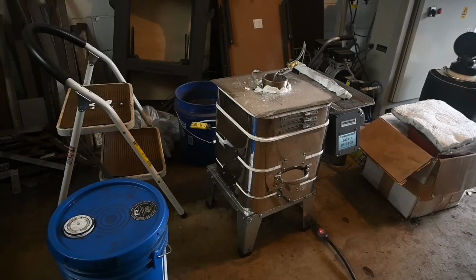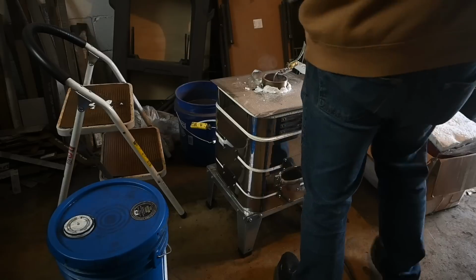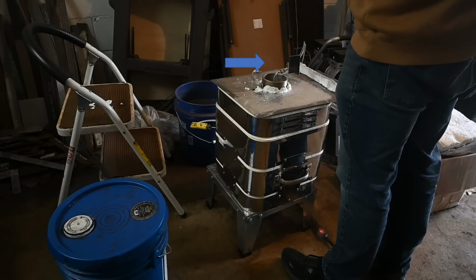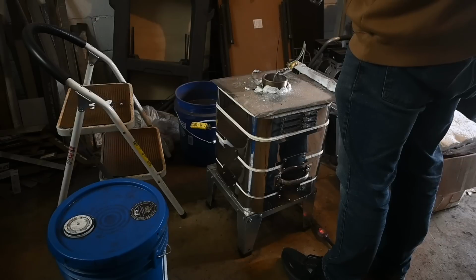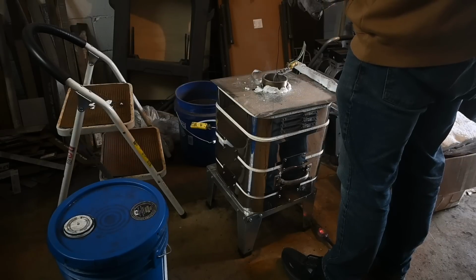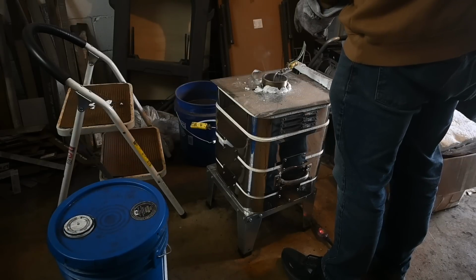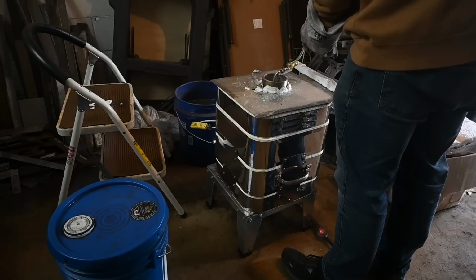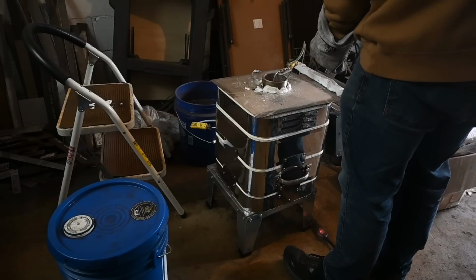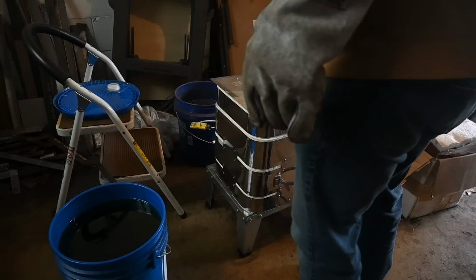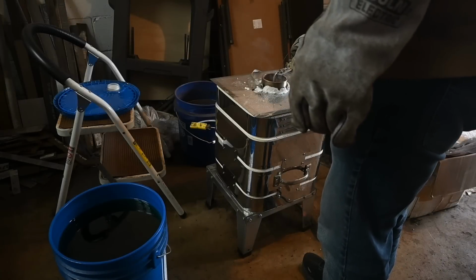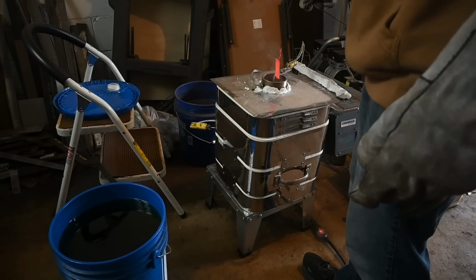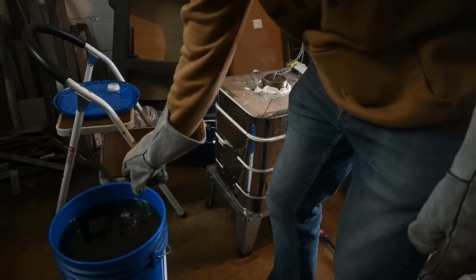So first, I wanted to measure how much faster can you heat up the steel in the salt bath as opposed to a conventional furnace in air. So I used coupons of 1084 steel that are about 1/8 inch by 1.5 inch by 2 1/4 inch or so. And I used a series of coupons and sticking them in 1 minute increments. So I did one for 1 minute, one for 2 minutes, one for 3 minutes, etc. And then I measured the hardness after quenching in Parks 50. I compared that with a furnace in air.